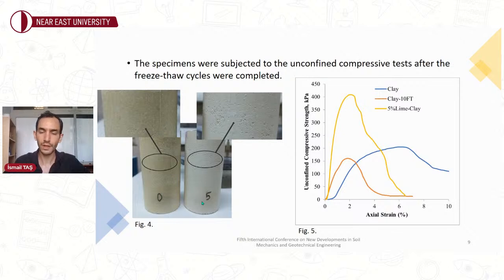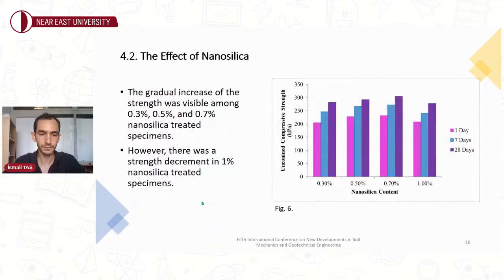In figure 4, you can see the change in the appearance of the specimens between 0 and 5 freeze-thaw cycles. Deterioration and minor cracks became visible. In figure 5, it is seen that the behavior of the clay has changed from ductile to brittle behavior with the action of freeze-thaw. In order to examine the individual effect of nanosilica on the strength, specimens containing different amounts of nanosilica were prepared.